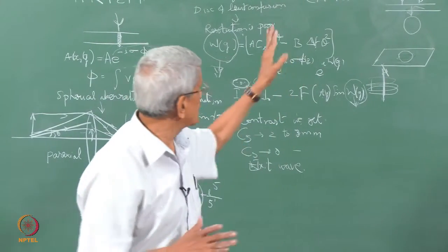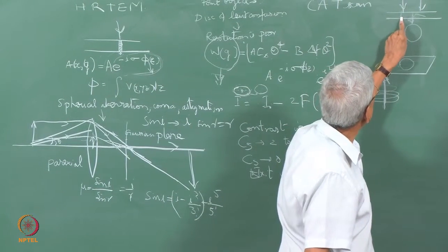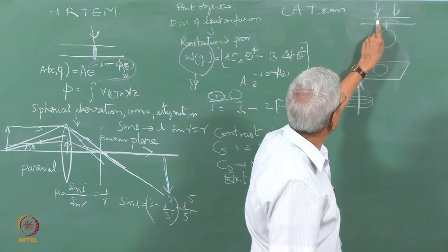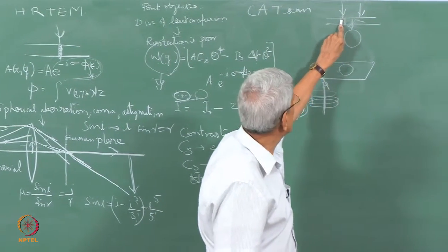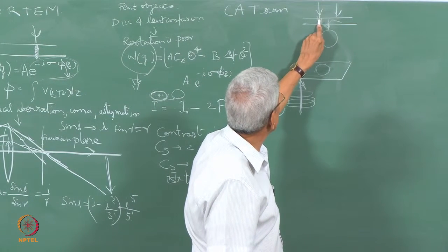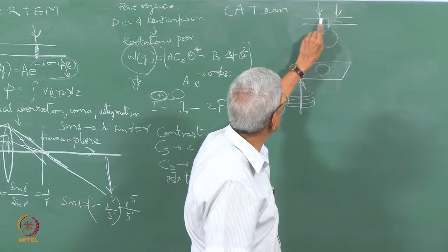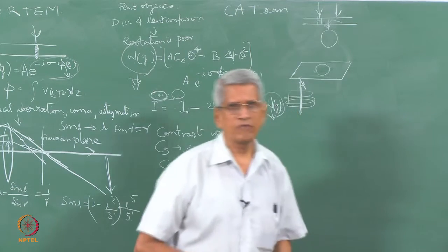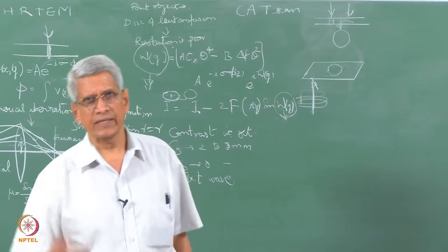Normally, as the beam passes through the sample, scattering takes place within the material depending upon the planes which are inclined with respect to the beam direction, whether they satisfy the Bragg condition or not. In addition to it, when a magnetic field is present, that will generate a Lorentz force on the electrons, and this will change the direction of the scattered or diffracted electron beam.